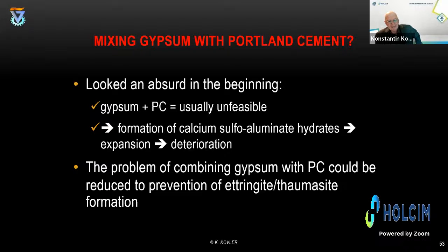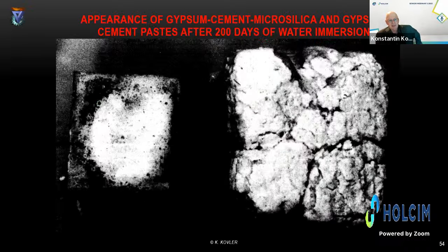And we tried to add some active mineral additives like silica fume to make peace between these antagonistic materials, gypsum and Portland cement, to avoid the formation of calcium sulfoaluminate hydrates, which result in expansion and deterioration. Here we just mix gypsum and cement. This is 75% gypsum and 25% Portland cement. In 200 days of water immersion, you can see huge expansion. The material loses its strength completely, cracked. And this is, of course, out of the way to implementation.